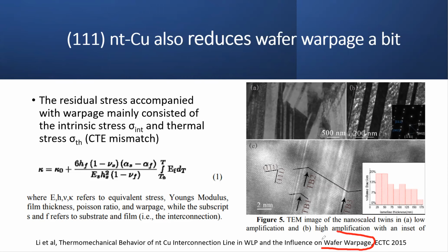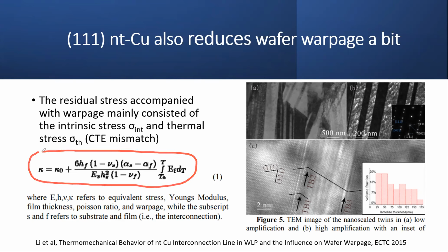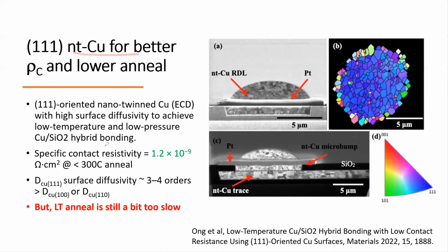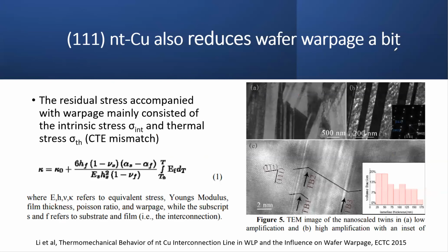So they tried to use this one to demonstrate that it improves. But is it good enough? Still not, maybe not, right? The famous formula for wafer warpage is calculated from the intrinsic stress and thermal stress. This is a well-known formula, calculated from the Stoney equation. So bottom line, this copper has the higher surface diffusivity. They move quickly on the surface, so it's easy to get rid of the voids. And then the contact resistivity is pretty nice, and they could also reduce the wafer warpage a bit. So they're pretty decent, pretty good. Whether it's going to be cost reasonable and fast and meet all the other criteria remains to be seen, right?